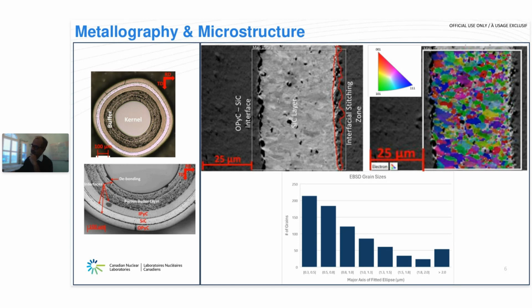In this image, you can see these are as-deposited coatings. There are some pores, which are deposition defects in the material itself. On the right, there is an EBSD map that is overlaid on this area. This particular type of silicon carbide coating is a cubic silicon carbide coating, 3C type.